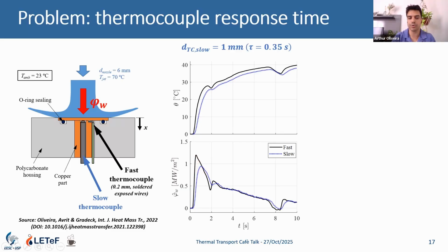So the method we propose can reconstruct the thermocouple response. You can see it's very close to the reference, the black line, and the estimated heat flux gets much better.